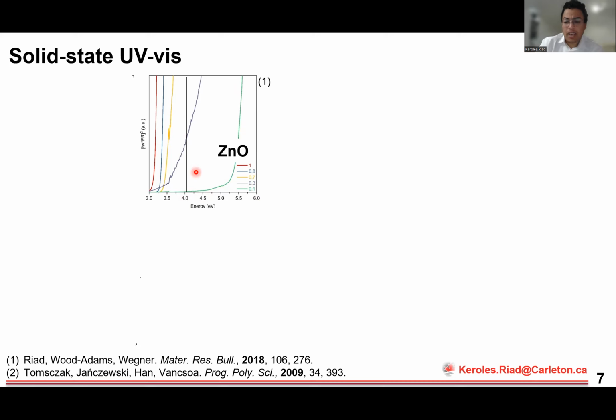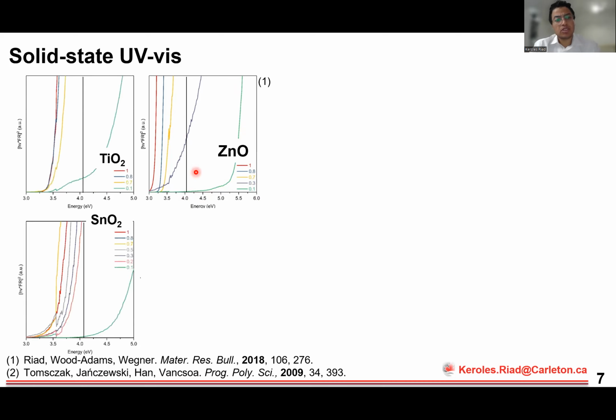I also tried to generalize this approach with other materials. So I also made quantum dots with titanium and tin oxide, and it's fairly consistent: as X decreases, you have a clear quantized effect where the band gap energy increases to higher values in both cases.